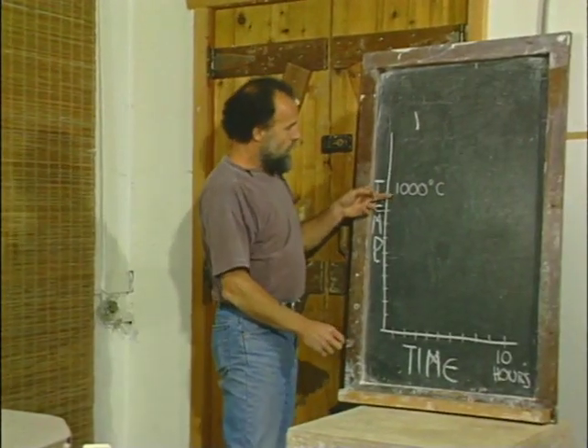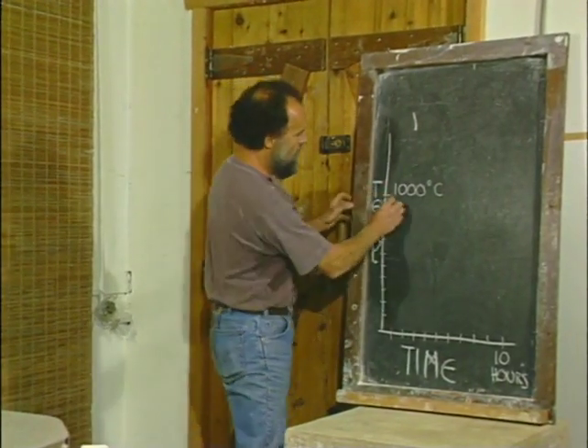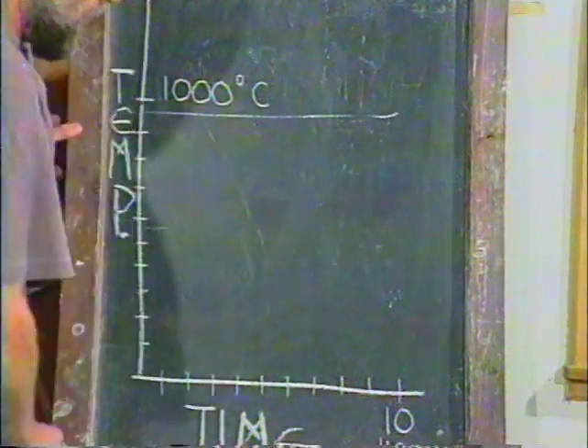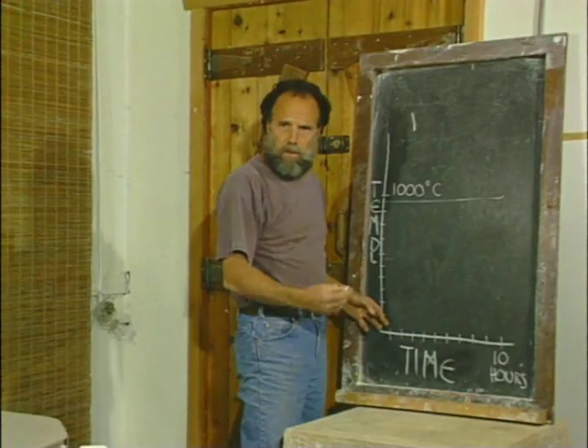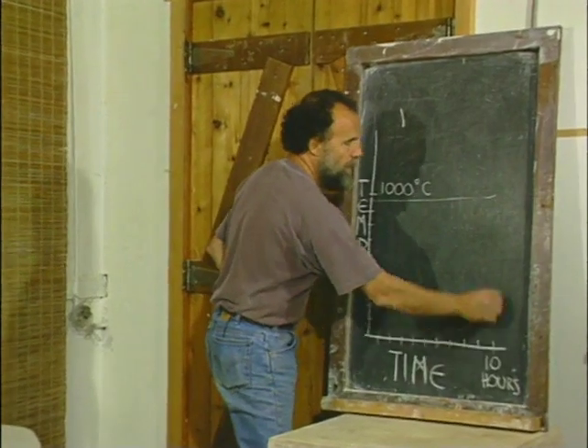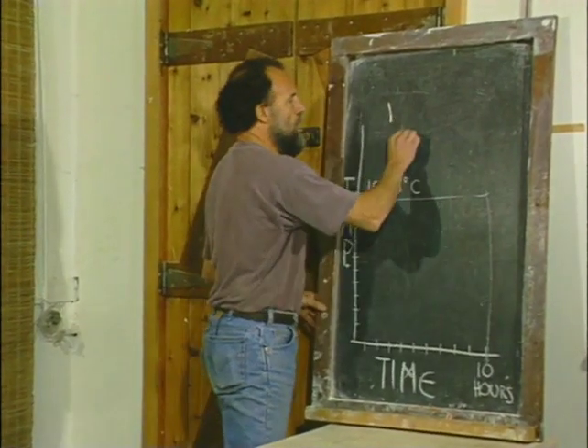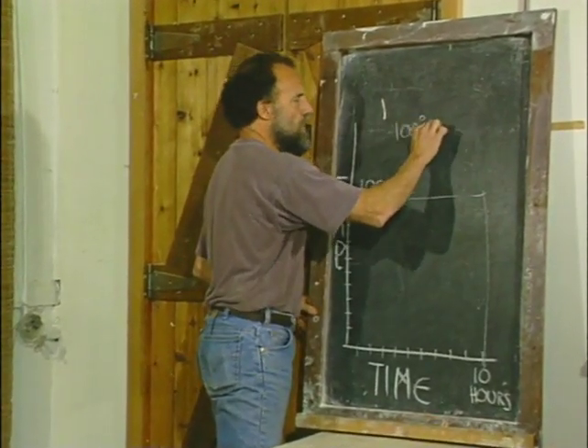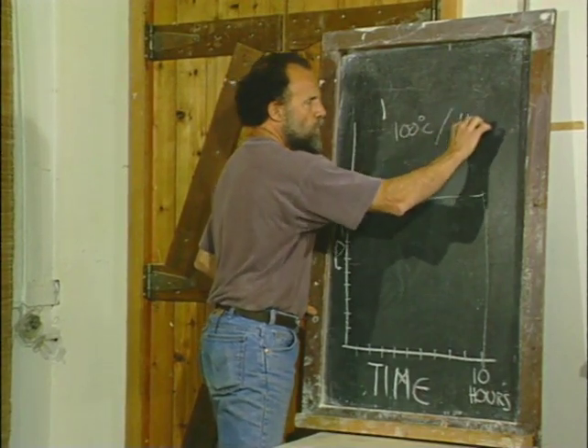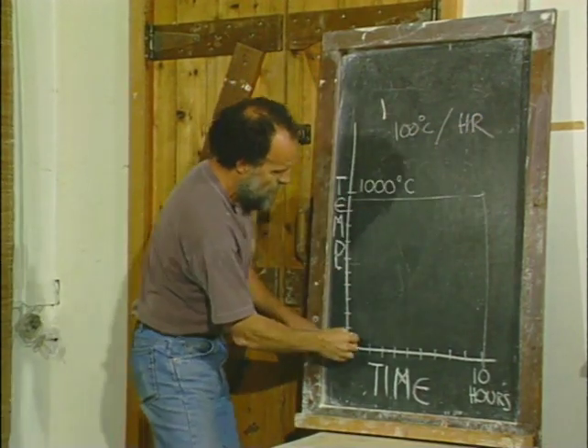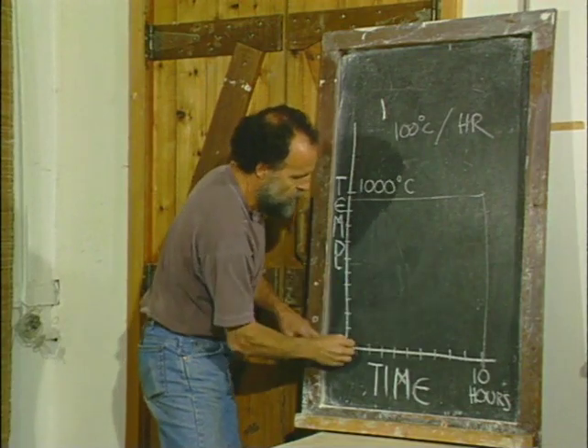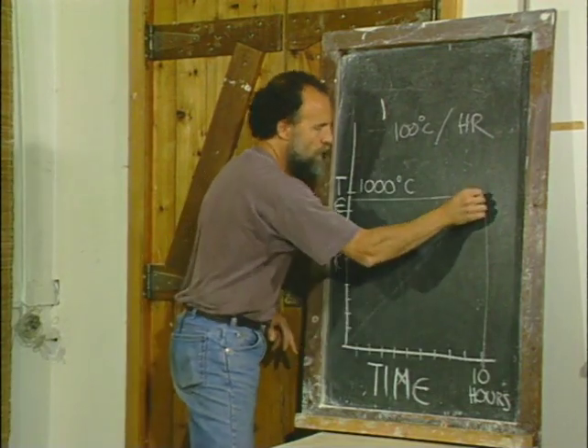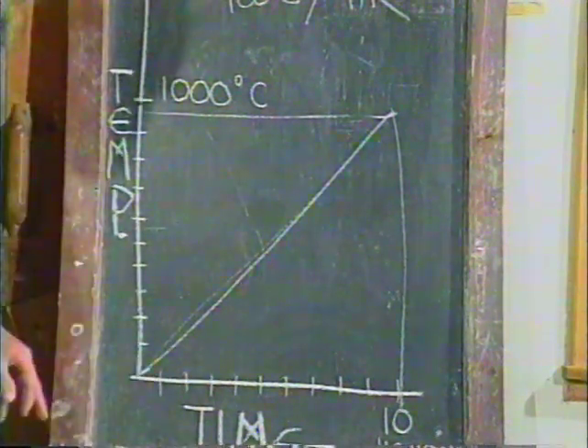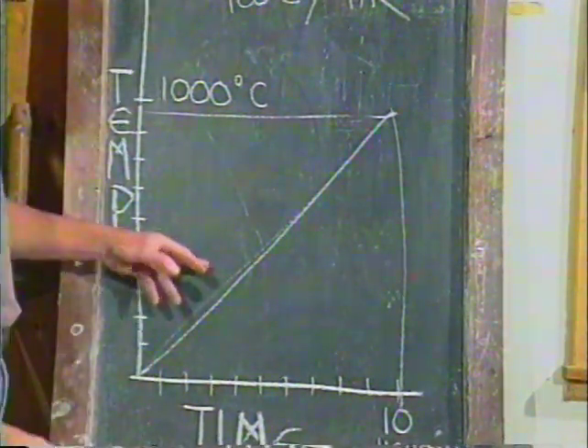Okay, we're shooting on this firing for about 1000 degrees, that's our cone 010, and a conservative time to get to that would be about 10 hours, giving you a rate of about 100 degrees centigrade per hour. Now, the actual progress of the temperature may not be quite linear, but let's draw in a line like that and see if we can't observe a few things.